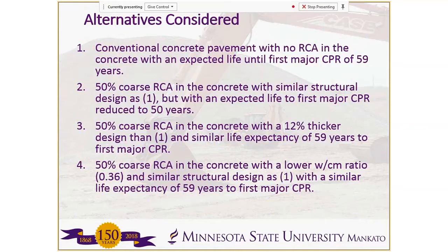The next 2 had 50% coarse RCA in the concrete. The third one was including a thicker design. We said one of the methods you can use to try and get an equivalent performance is to make the pavement thicker. So in number 3, we had a 12% thicker design. Number 4 was also 50% coarse RCA, but here we lowered the water cement ratio to try and get equivalent performance with the conventional.